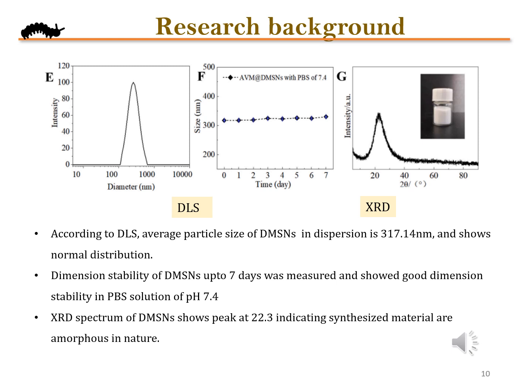Later, XRD analysis was performed to know the lattice parameters and structure of the material, and the peak at 22.3 indicates that the synthesized material is amorphous in nature and stable.